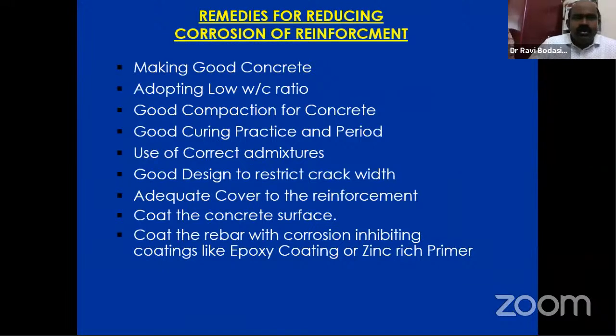So how do we get rid of this corrosion? Make good concrete: adopt a low water cement ratio, good compaction of concrete, curing practices, and use correct admixtures. Why? Because some admixtures also contain chloride content and sulfur. So use the correct admixtures for the cement you are using, and check the compatibility of admixtures with the type of cement you are using.